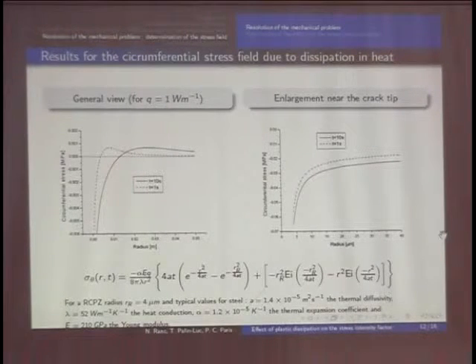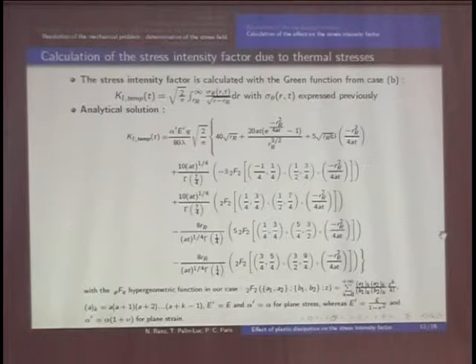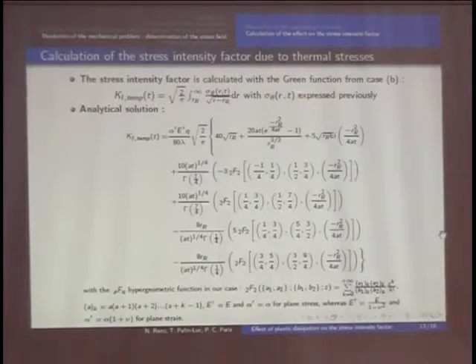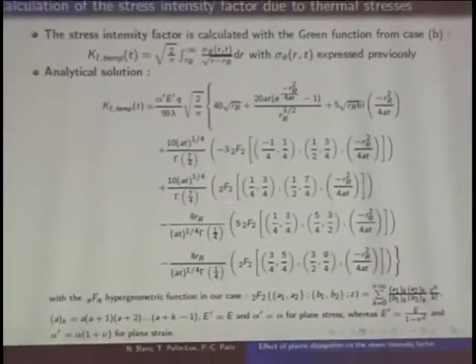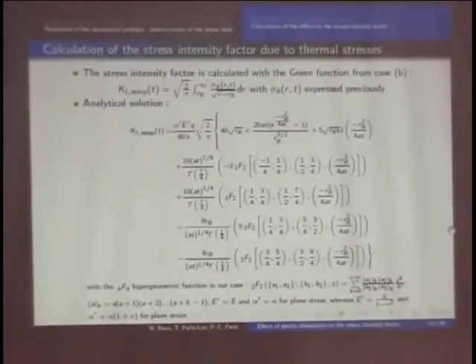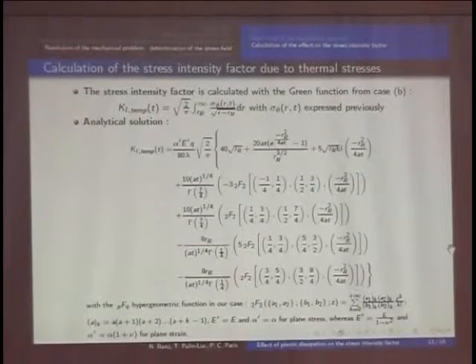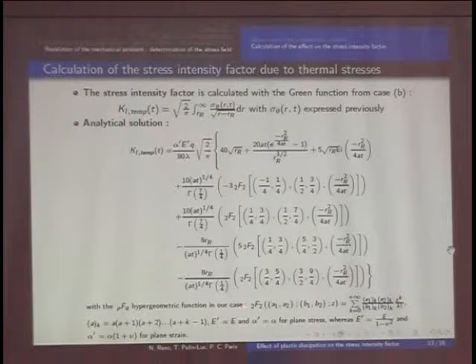Now, with this stress field, we can include it in the stress intensity factor calculation and see what happens. The stress intensity factor has been calculated with the Green function in the case of the semi-infinite crack in an infinite plate, with the thermal stresses due to the heat source. It's interesting in this case that we obtain an analytical solution. Of course, numerically, with finite element analysis, we can solve, but here it's interesting to see the tendency and what are the important parameters. In this analytical solution, where the f function is a hypergeometric function, we can see that Q here is a key parameter, and the lambda also is an important parameter.